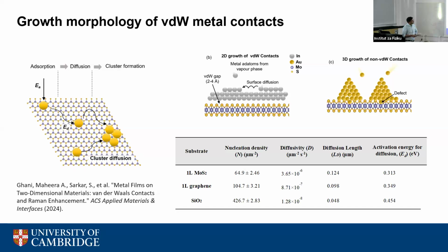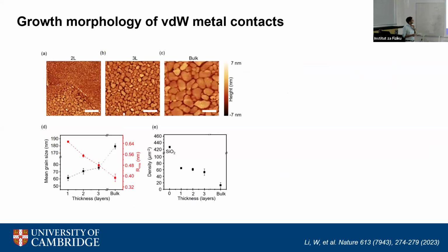We did some calculations of what the nucleation density is for indium. You can just do an AFM or SEM image and calculate the number of grains. I'll show you some images later. For indium on silicon oxide, we have around 426 grains per square micrometer, while for MoS2 and graphene it's relatively reduced because the surface of MoS2 and graphene is much flatter compared to silicon oxide. In some AFM images, this is, I think, 2-layer MoS2 on silicon oxide, and we have grown 5 nanometer indium. This is just the topography of the image. You can see that the indium forms really small particles on silicon oxide, but when it grows on MoS2, the grains are much larger, and they grow laterally because there are fewer defects.